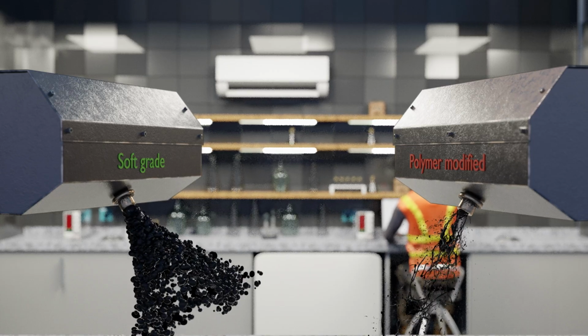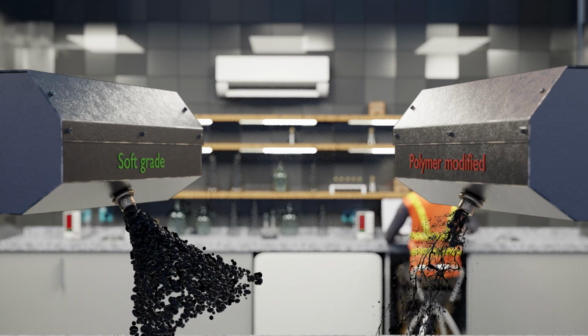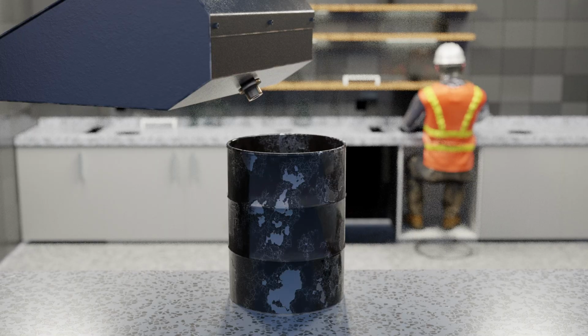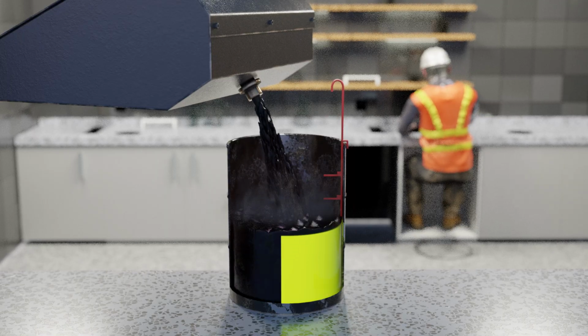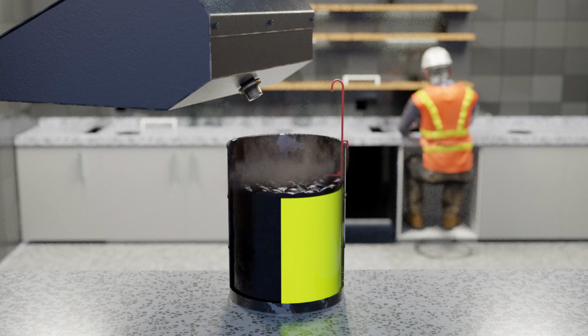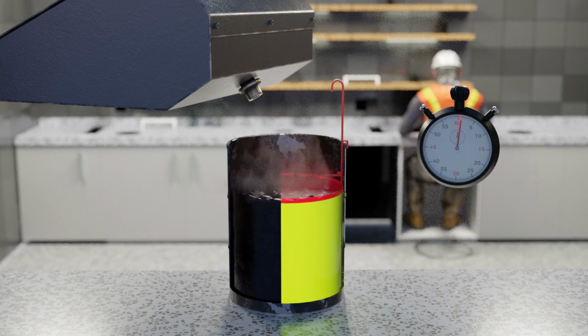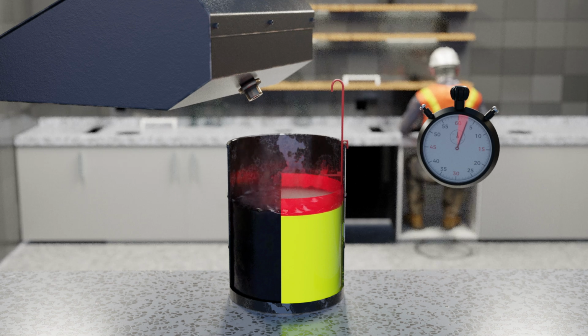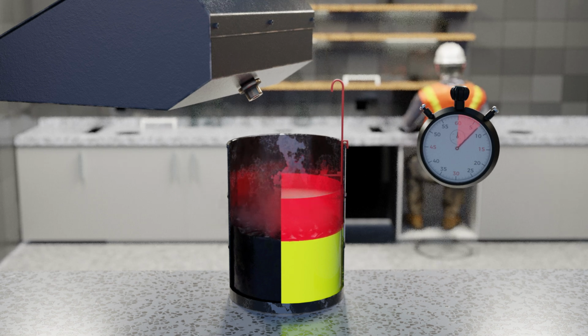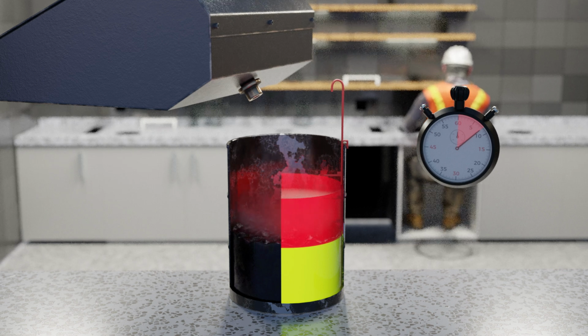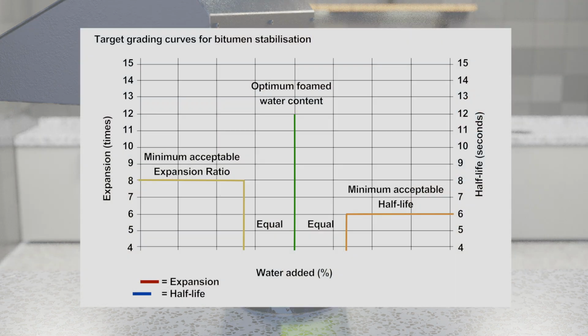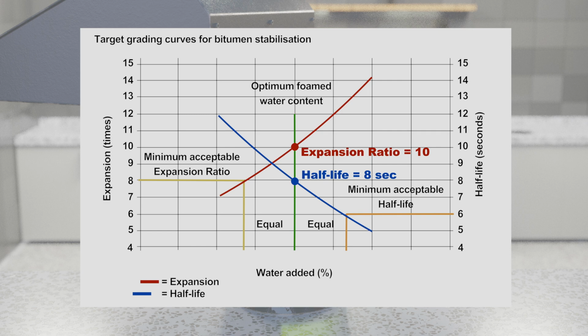The foam quality is described by the expansion ratio and the half-life of the foam. The expansion ratio is the maximum foam volume divided by the original bitumen volume. The half-life indicates the foam stability and is measured as the time for the foam to collapse to half its maximum volume. These properties are influenced by the bitumen type, temperature, and water content. A typical foamed bitumen mix achieves an expansion ratio of 10 and a half-life of 8 seconds.